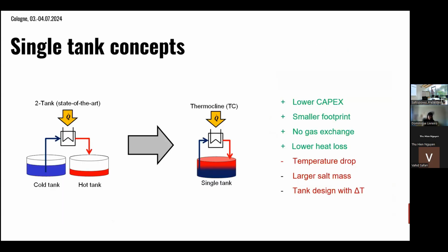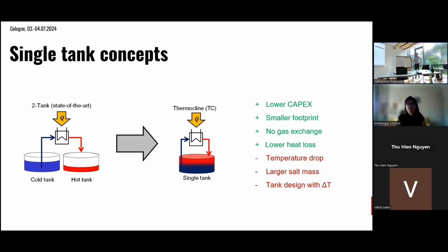Now, what we are looking at is different single tank concepts, starting from the state of the art, the 2 tank concept. The first concept we've been testing was the pure thermocline, where you put both hot and cold salt together in one tank and have it separated just by density differences. The hot salt is about 10% lighter than the cold salt, so you can have some sort of separation and a thin layer of transitional zone between the hot and the cold. In general, this has some advantages because you have only one tank instead of 2, with a lot of cost savings,